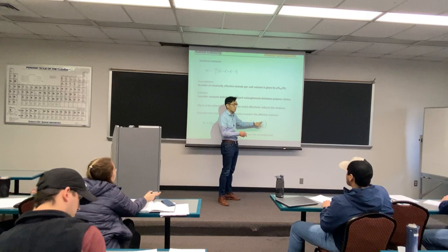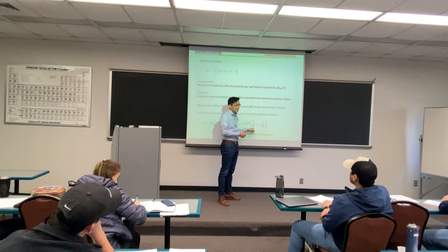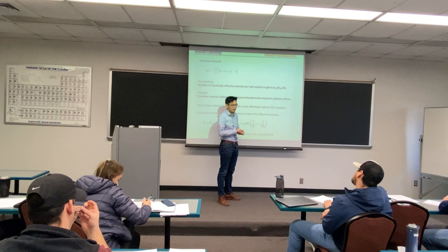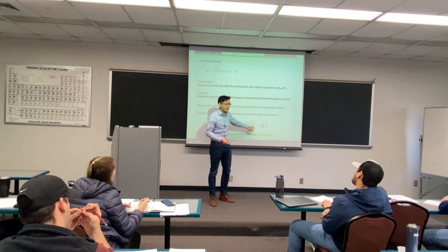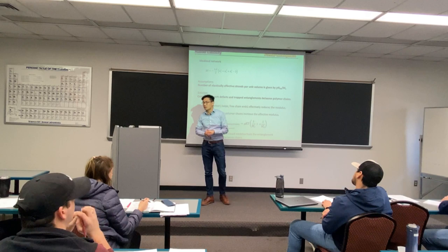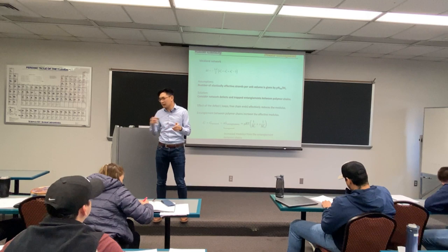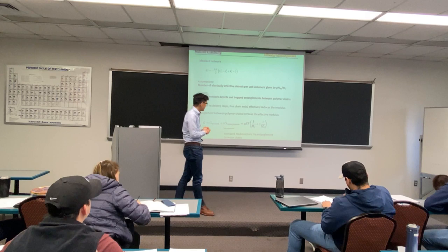This is 18K. That means if your polymer is more loosely cross-linked, let's say your Mx is 180K, with or without considering entanglement is a huge difference. It's a factor of 5 if you do the math. That means your entanglement increases the modulus by 5 times. However, if your cross-linking is very high, then this term dominates and this term doesn't matter. This happens in the highly cross-linked case. If your molecular weight between the cross-links is within, let's say, 1K, which is highly cross-linked, entanglement doesn't happen. You can also think about it in the shorter chain, you're less likely to have any entanglement. Okay? So those are the several theories developed to better describe what people observed in the rubbery material.